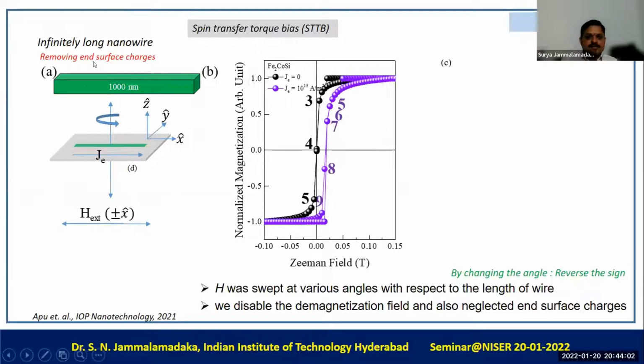Okay, so basically what we have done is we have taken an infinitely long Fe2CoSi nanowire. That means an infinitely long wire, in the sense that we removed the surface charges at the edges. And then we tried to send the spin polarized current through the nanowire, and then we tried to change the angle between the magnetic field and the nanowire length.